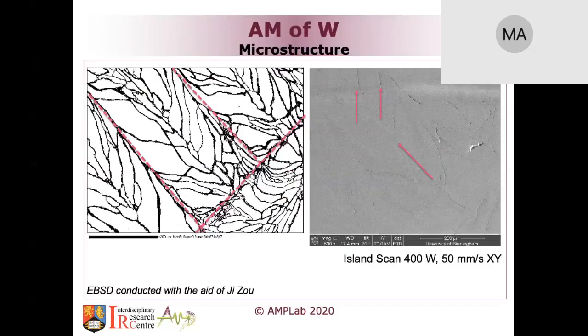So yes, we can get some conditions, as you can see, that are fairly dense. Yes, we do have the cracks, but again, good density, with some cracks. And cracks, as I mentioned to you, do form at the edges of the melt pool. This is a melt track, as you can see on the EBSD map, and you can see where the cracks are forming. It is indeed because the oxygen gets rejected to the melt pool boundaries, as you can see all around the melt pool boundaries, and also in the center of the melt pools, and that leads to the formation of cracks.